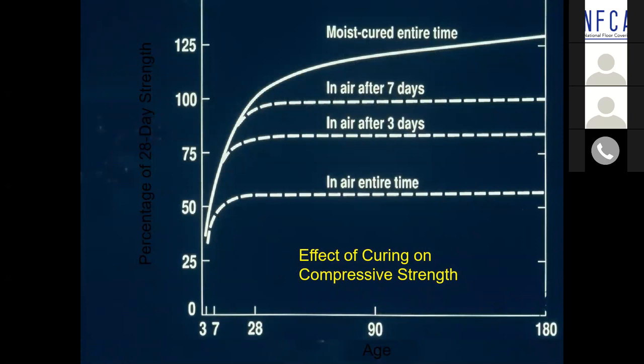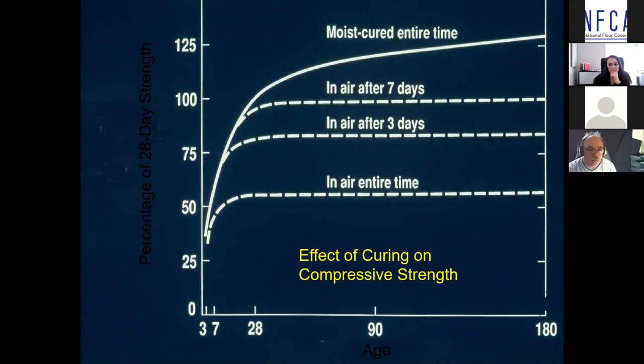This is a graph or a chart of a study, the summary of a study that was done at the Portland Cement Association in Skokie, Illinois, some years back, where they went out in the backyard and they placed 4 different concrete slabs. The line in the bottom, what they did is they placed it and did no curing whatsoever. So it was exposed to air the entire time. The next one up that you see at about the 75% level, the slab was wet cured for 3 days, then exposed to air. At the 100% 7-day level, you see they kept it wet for 7 days and then exposed it to air. And the top curve that continues to rise, they kept it wet for 180 days.